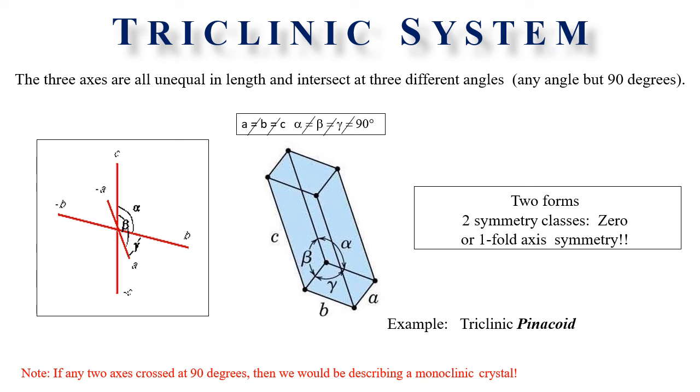There has been no standard way to orient triclinic system, and even for the same mineral many different orientations have been used. Thus, for axinite more than a dozen settings are recorded. One such is in fact a:b:c equals 0.49:1:0.48, alpha equals 82 degrees 54 minutes, beta equals 91 degrees 52 minutes, and gamma equals 131 degrees 32 minutes.